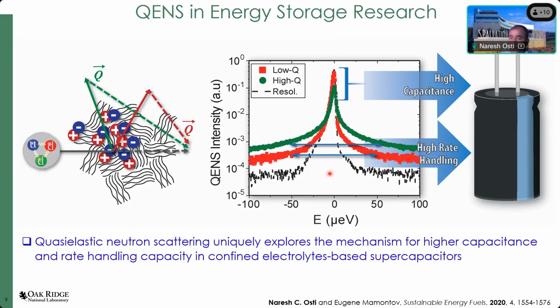That diffusion coefficient can be related with the rate handling ability of the device, and the intensity difference that you get at the zero energy transfer, which is coming out from the immobilization of the ions on the surface of the electrode, which you can relate to the capacitance. That's how we can make the connection with the electrochemical performance with that of the information that you get from the quasi-elastic neutron scattering technique.